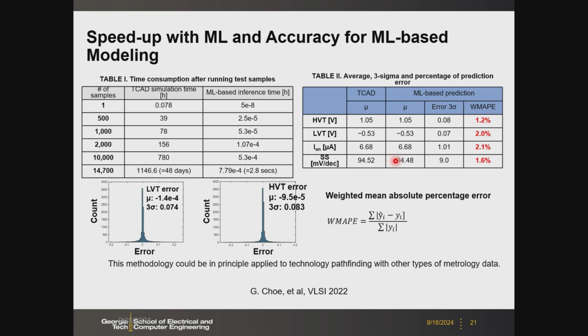Imagine that you change your process condition. You run a new wafer, you get the new thin film data, then we don't need to redo this again. Of course, we have to do some in-line metrology and TKD pattern. After we get the pattern, we can quickly run this machine learning model to infer whether the quality of the thin film for this run is good enough to move to the next stage of further device fabrication, or we can discard this one and fine-tune your process condition, your annealing temperature or whatever, to improve the quality of your polarization variation map. Then we can basically use this as a way to speed up the material screening without doing the entire flow of the transistor fabrication.